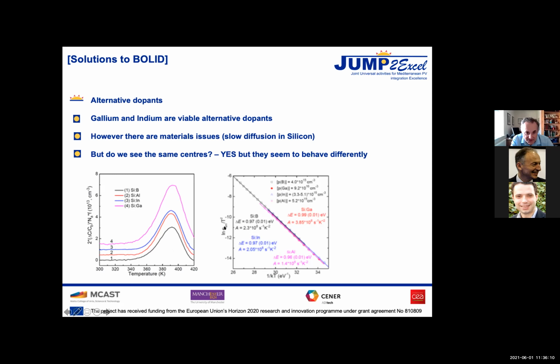But the behavior, so this is a capture cross section. The capture cross section changes. So we think that they're structurally similar. We think that these metals from this group of the periodic table commonly form a complex with two oxygen atoms, but they are not electrically identical in their behavior. And for some reason, the boron degrades the activity of the cell. So that's ongoing research. We're still looking into that.